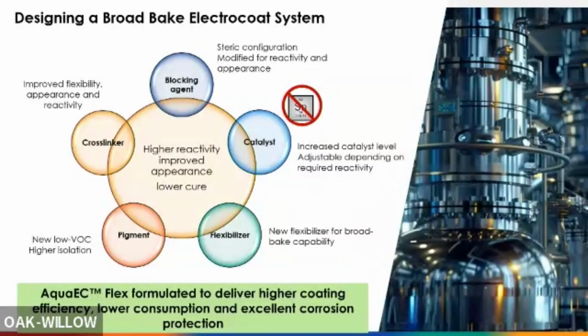Now for the how. Again, without giving away some trade secrets, we took the entire system apart and we basically redid the polymer architecture, changed the molecular weight, changed the end capping groups, changed the amine, went to a lot of crosslinker and isocyanate chemistry, and then a lot of the magic actually came from some of the catalysis work, right? If you read the patents, all of us paint suppliers are in the same catalyst family, but it's the way in which we create that catalyst salt, that's where some of the differences lie. If you do it in the right salt formation, the molar activity and effectiveness of the catalyst changes, right? So I can use less moles and still get the proper cure.